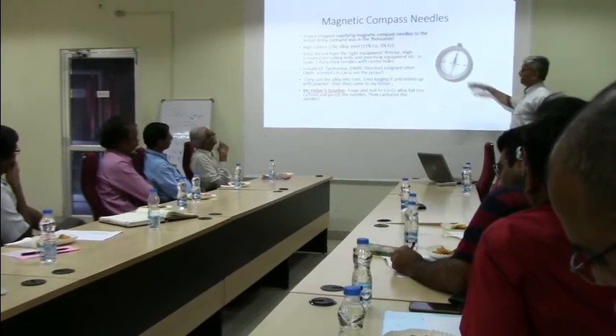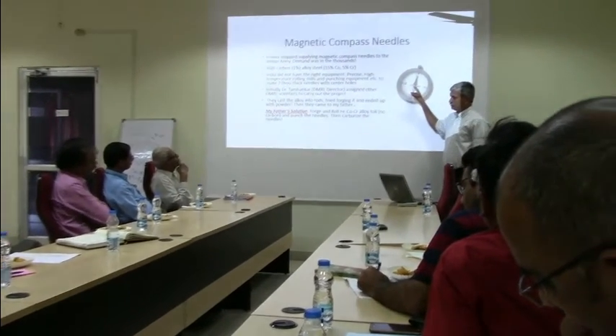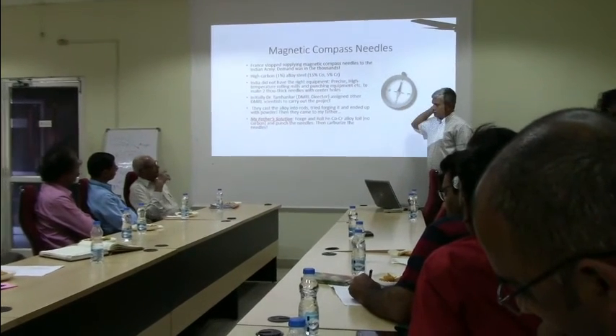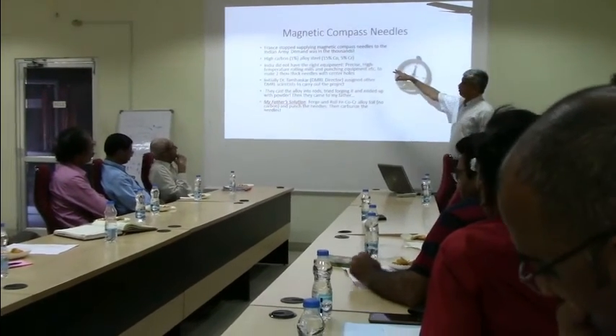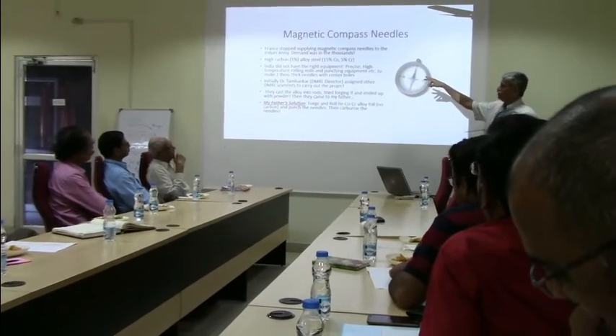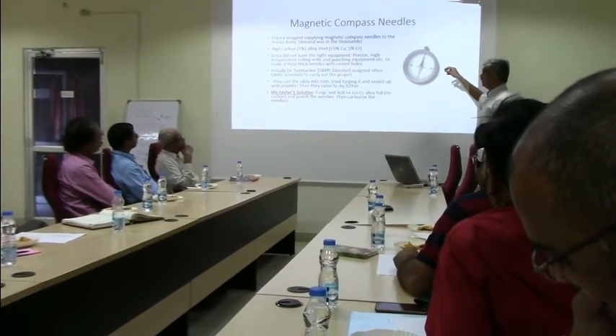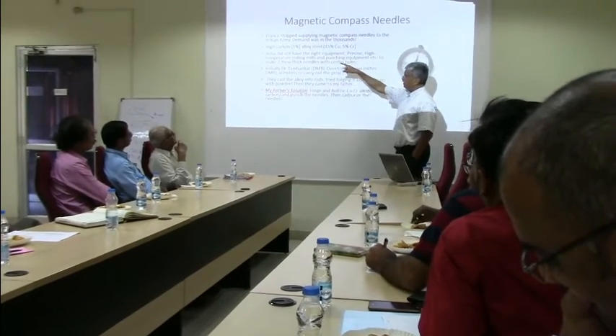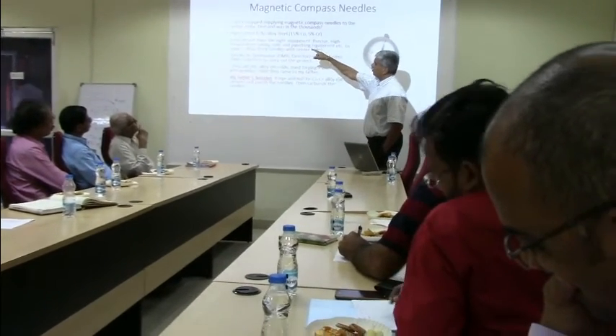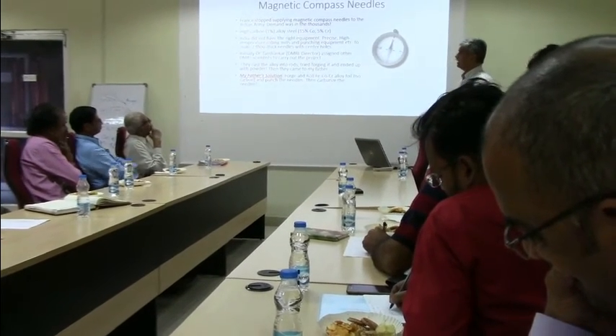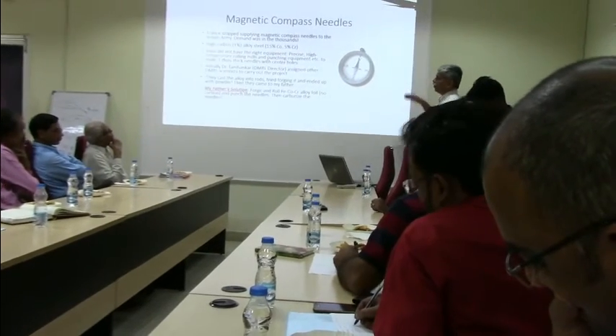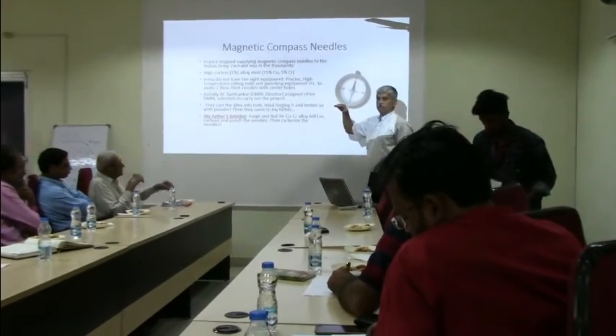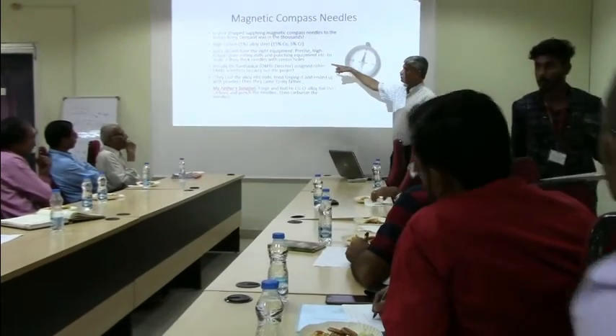So, in '65, when did France stop... With Pakistan. Yeah. So France stopped supplying magnetic compass needles to the Indian Army, and the demand was in thousands. Now this compass needle has a very interesting combination. It's a high carbon steel, 1%, with also very high alloys. What they do is they roll this in the austenitic condition. When it's in an austenitic condition, the steel is very soft, and even though it has 1% carbon, it can be rolled into very thin foil.